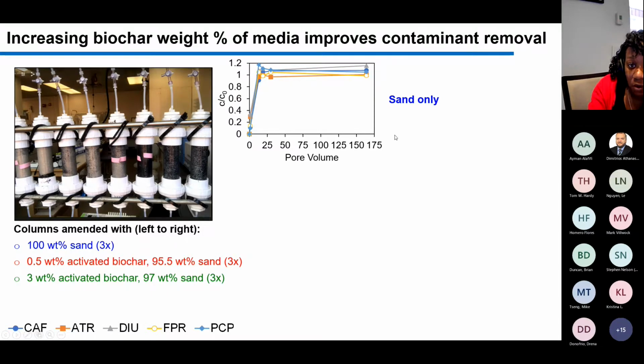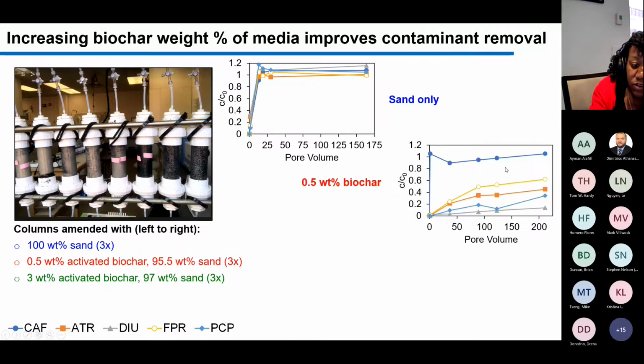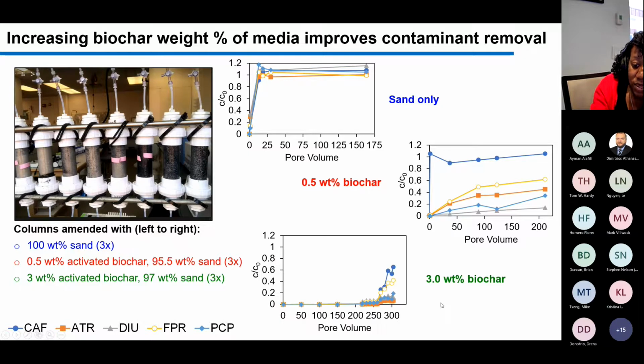Values of 1 means that whatever contaminant you put in is coming out of the column, so no treatment. So not surprising here, when we have sand only, there's this rapid breakthrough. So the contaminant that enters the column just exits the column rather quickly. And we're not surprised there. We know that sand is not great in terms of removing trace organic compounds. When we slowly start to increase the amount of biochar in the system, we see that for some compounds like caffeine, that happens to be pretty hydrophilic, we have more or less immediate breakthrough compared to some treatment of the other representative urban stormwater contaminants. And then when we increase the amount of biochar in our columns further to 3%, you can see that we're able to treat many, many pore volumes of stormwater in this case, and these columns are still operating, and we are still removing contaminants, even with just 3% biochar, which happens to correspond to about 4 grams of biochar in a column packed with 200 grams of sand.